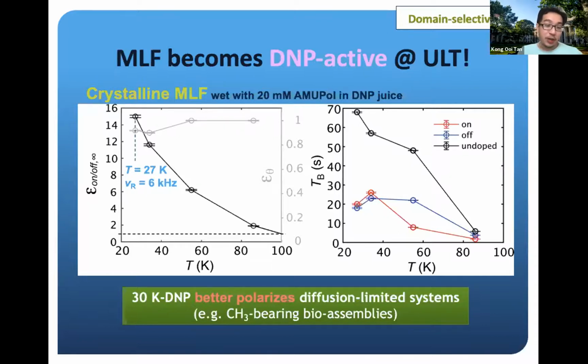I think the former grad student in our group, Cheng, tried all this on bacteriorhodopsin. And we found that deuterating all these side chains, the methyl groups, actually improved the DNP. And not only that, it's interesting that at low temperatures some of the methyl group three-site hop rotation will interfere with MAS, then your 13C peak will just disappear. And if you cool to lower temperature, it comes back again.